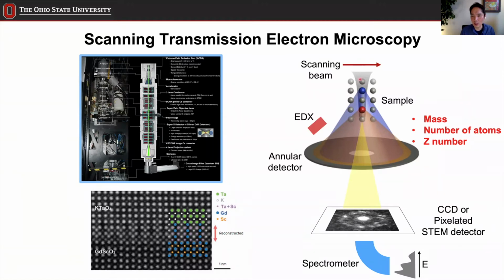And what happens is that the incoming electron is going to interact with those atoms, more specifically the electrons that orbit the nucleus. That interaction provides the scattering events, right? Those scattered electrons scatter in many different ways, and we place detectors in many different positions to get the scattered information. Depending on where you get the scattered information, that provides different information. For example, if you have a CCD type detector placed directly underneath the electron beam, it gives you a diffraction pattern, which is very similar to an X-ray diffraction pattern or neutron diffraction pattern. Or you can have a spectrometer underneath to analyze the energy loss of the incoming electron by the interaction, to have some chemical sensitivity so that you can tell, okay, this atom is gold, that atom is silver or iron, etc.